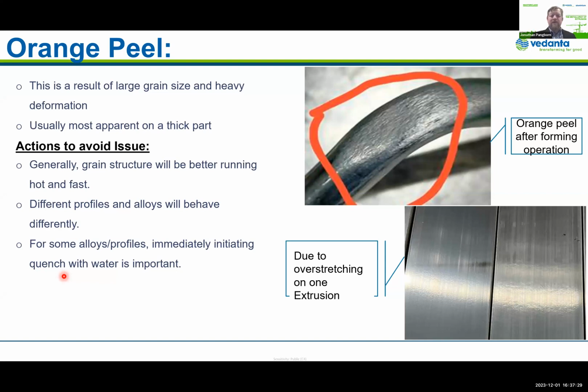I would say generally no, but there are many factors that go into it. The more energy that you can put in, and it's not electrical energy, but energy of work that you put into the material, the finer the grain structure is going to be. And you can put that energy in really two ways, with temperature and with work for deformation, which is your strain, but it's also related to the resistance to deformation of the material. So as you go higher in billet temperature, you're starting with more energy in the material to begin with, but the counterbalancing factor is that it's also easier to deform, so you're putting in less work energy, right?